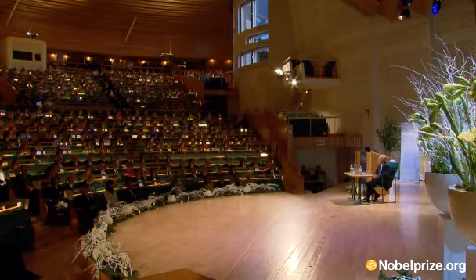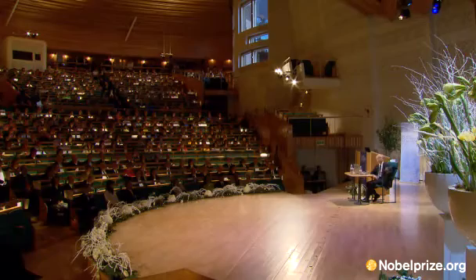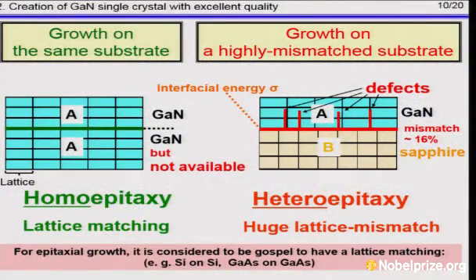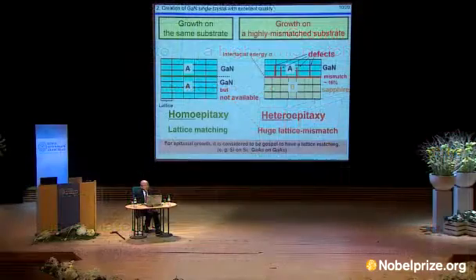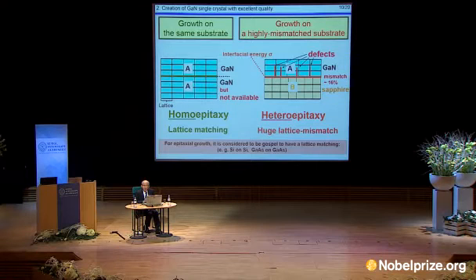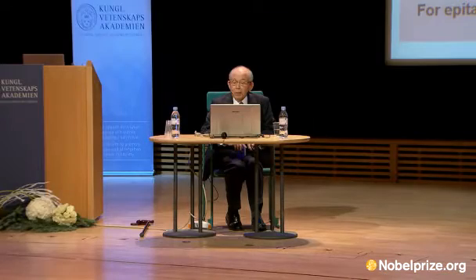Even though the film thickness was now even for the entire wafer, there was no substantial improvement in electrical and optical property either, which suggested the presence of a lattice defect and impurities. This would be, for the most part, due to the huge lattice mismatch of 16% between gallium nitride and sapphire as substrate, I suspected. In fact, for the epitaxial growth of semiconductor, it is considered to be gospel to have lattice matching as growth of silicon on silicon. And in the case of a heteroepitaxial growth, even a mismatch of 1% would make it difficult to grow high-quality single crystal.